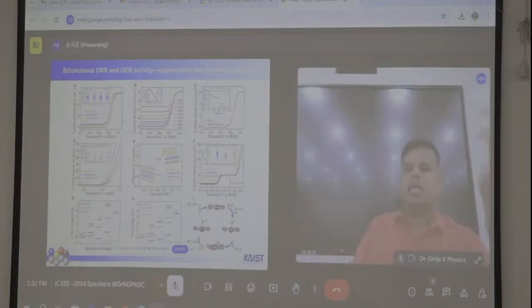The half-wave potential shifting towards the positive region means higher kinetics as well as higher ORR performance compared to the other catalysts. So in order to compare the ORR catalyst, we have to use commercial platinum carbon, to see whether it is better than commercial platinum or poorer than platinum. In the case of our optimal catalyst, it has higher performance than platinum, and we also tested at different rotation speeds. When increasing the rotation speed from 400 to 3,200, the current density drastically increased.